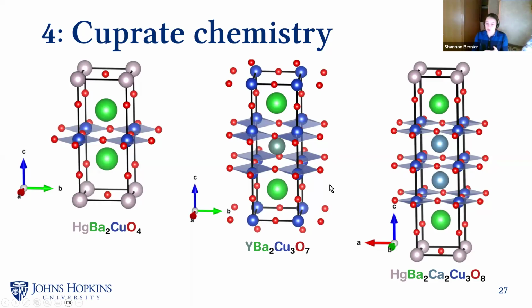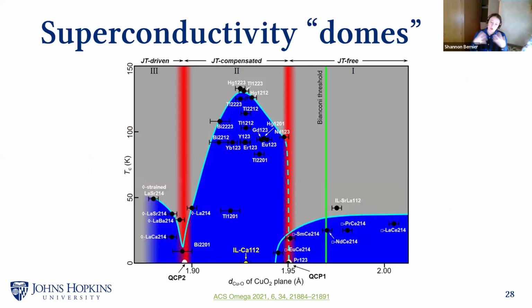There are many different classes of superconductors in the cuprate family. They have different numbers of these planes in different locations, different spacing atoms in between them, and they all have different transition temperatures. But even knowing that the presence of a copper oxide plane can be important, it's still difficult to predict what the superconducting transition temperature will be. We call this TC. And one of the common ways that people try to do this is they try to plot some factor that they know to be important along with the transition temperature. In this case, they've plotted the spacing of the copper and the oxide in the copper oxide planes. And when you do this, you end up with these three quote unquote domes.